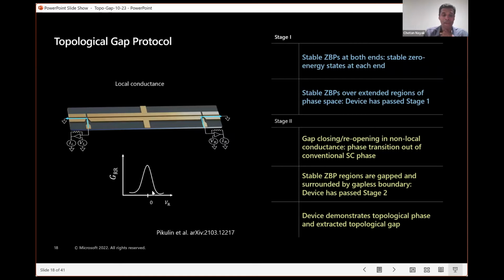What we're looking for are zero bias peaks. When this conductance is peaked at zero bias, that means there's a zero energy state in the wire that we detected through this conductance measurement. We want them to be stable at both ends of the wire, so we want to see them at both ends. We also want them to be stable over an extended region in phase space, the bulk phase diagram. So they need to be stable with respect to opening or closing these junctions more, changing the junction transparencies, and also stable with respect to pushing up and down the plunger gate voltage to change the average density, and also magnetic field. So we'll find regions in phase space this way that have stable zero bias peaks.